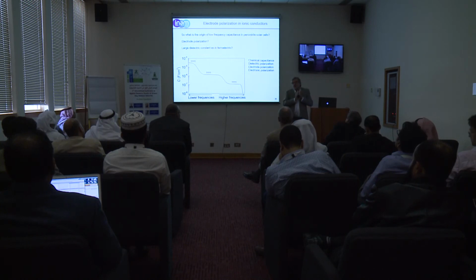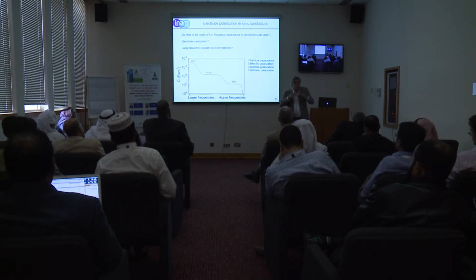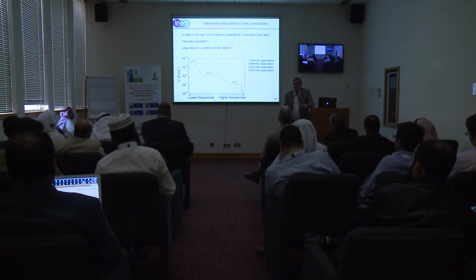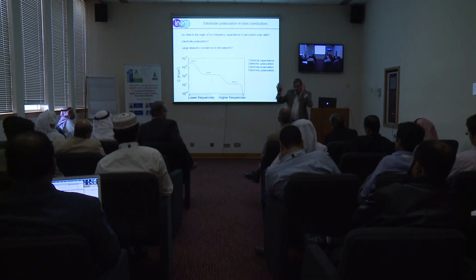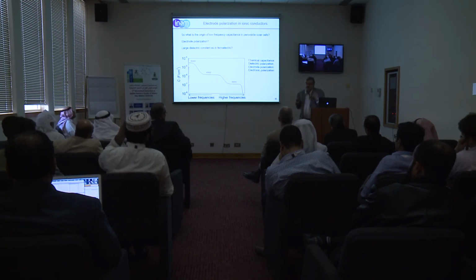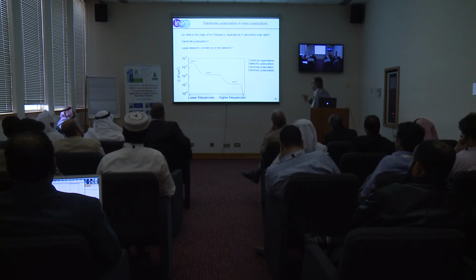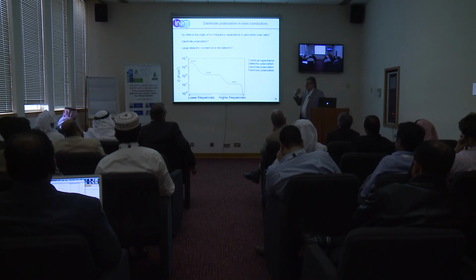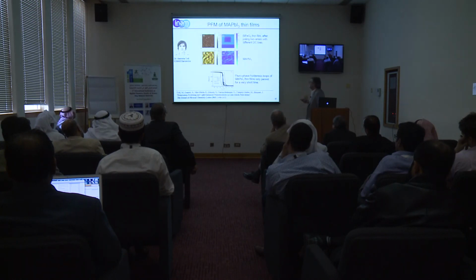These things have a very big difference. For chemical capacitance, when you make more material, you will put more electrons, and you increase the chemical capacitance. On the other hand, the electric polarization is totally different. You remember the textbook of physics, the electric capacitance is separation of positive and negative charge. When you make more separation, the capacitance goes down, okay? Because the electric field is going down, because the distance is larger. So the dependence with thickness is opposite, and this is something very good to see what is going on. Then we can have electropolarization, which is a candidate to explain this big one, and then we can have some other electronic polarization other than bulk chemical capacitance.